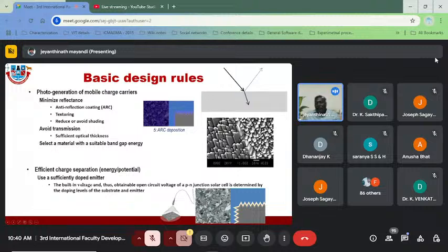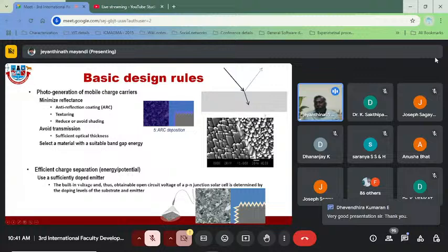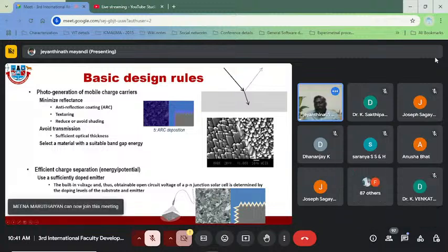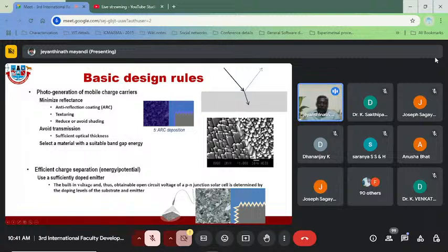To capture the light, the industrial process is to use an acidic or alkaline etch to make a pyramid-like structure on the top of the surface. Before doing this, you need to etch the wafer and remove the cracks in the wafer. Normally, as I said, the wafer thickness is almost 325 micrometers. After etching the wafer using a chemical polishing etch, you will have about 275 micrometers. On the top surface of the wafer, you need to make the silicon pyramidal structure so that total internal reflection could happen, and then the photons stay a longer time and generate more electron hole pairs in the material. So that is the first process.